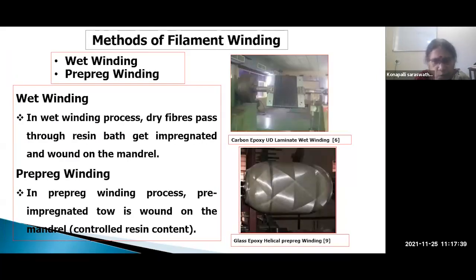Then there are two methods, as I told you, prepreg winding and wet winding. In wet winding, unfortunately, I'm not able to show you the resin bath because it is at the backside of the machine. So in wet winding, dry fibers pass through a resin bath and get impregnated and then wound on the mandrel. Whereas in prepreg winding, the pre-impregnated towpreg will be deposited directly on the mandrel. Here, if we use towpreg, we'll get good properties, good resin content. So the required volume fraction we get, density will be good, a sound component without much defects we get. So compared to wet winding, prepreg winding is better.